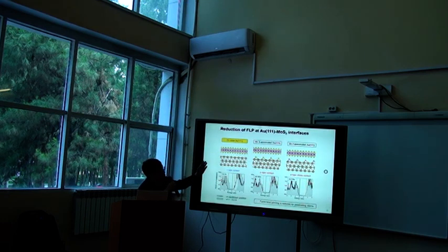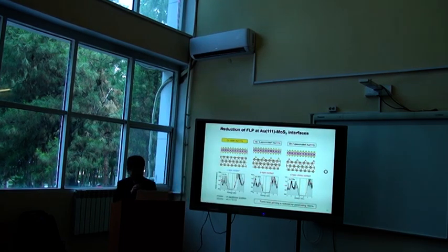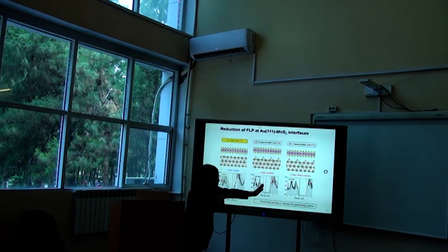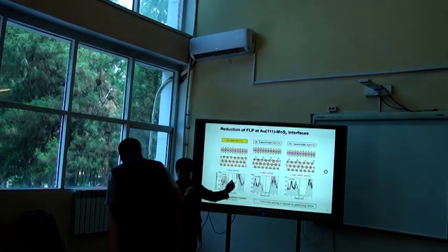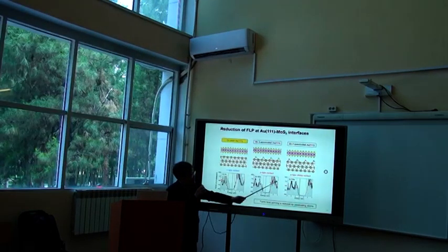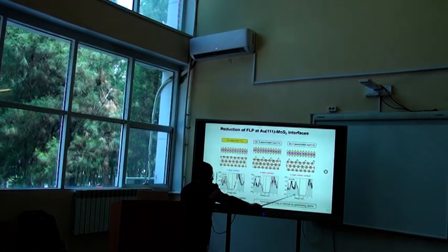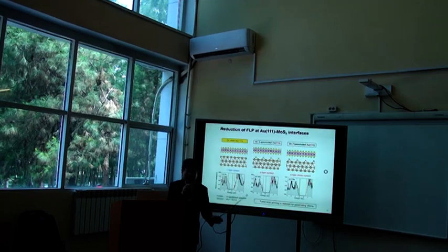And using the atom-passivated case, now you can see this Fermi level close to the valence band maximum, which shows P-type. And in the other case using the fluorine species, the Fermi level is almost at the valence band maximum, which is P-type, even ohmic contact.